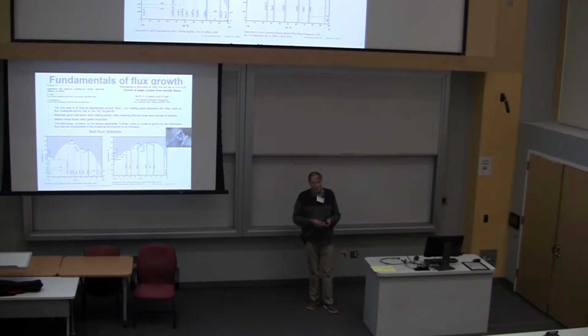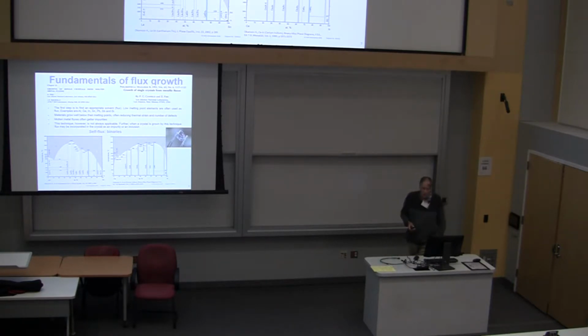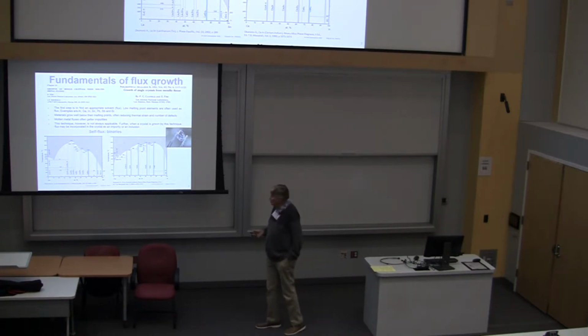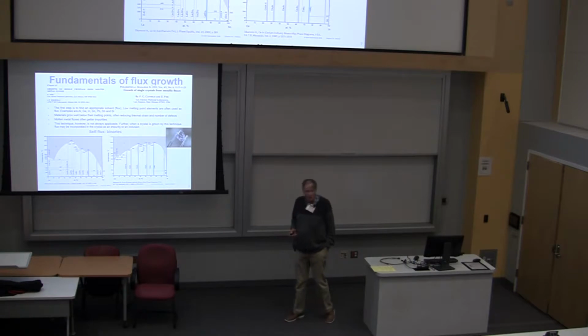Heat it up and watch when it starts to react. Lights up just like a light bulb. It just goes, and that's enough to crack your crucible. And so the way you get around that, if you're trying to grow things in a flux, for instance, you might say, well, maybe I can grow a lanthanum platinum compound in molten tin, rather than trying to make LaSn3.